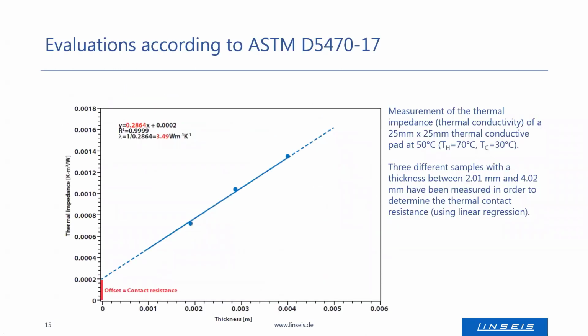As mentioned, one determines the thermal impedance with the heat flux, and this is repeated for several sample thicknesses. One needs to measure at least 3 different sample thicknesses because one has to plot it like that. So the thermal impedance is plotted dependent on the sample thickness, and this is a linear correlation. The more different thicknesses are measured, the more accurate this linear fit will be.